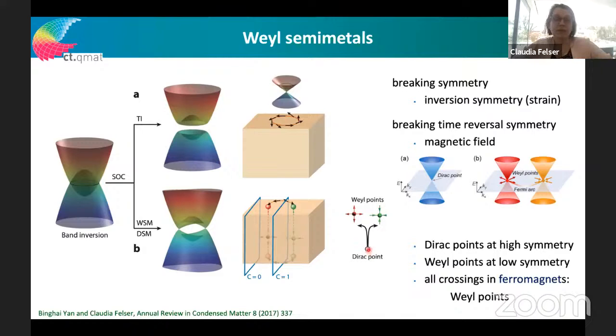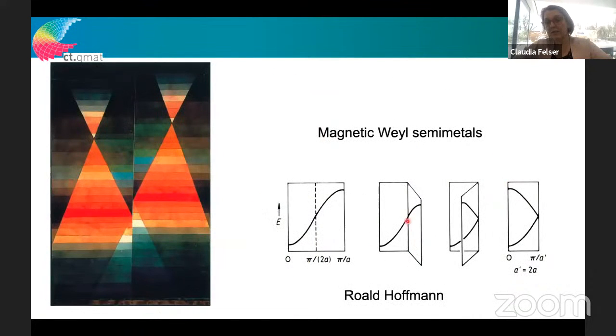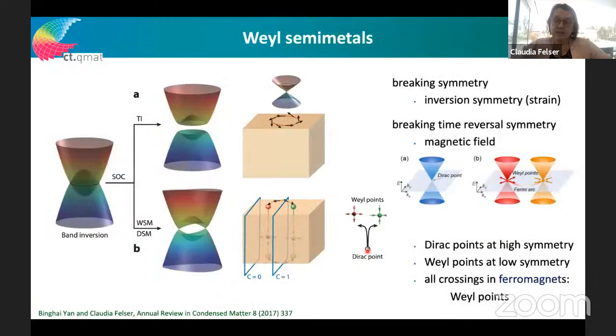Dirac points are 4 times degenerate, and they are at high symmetry points. We know this from graphene or from my nice simple picture here. If this is at the center, at a special point in the Brillouin zone, it is easy to find. And like in graphene, we have exactly the point at the K point here. So then we have it at this high symmetry point, it's 4 times degenerate. If we would now strain our graphene, we would lift this degeneracy and would end up with two 2 times degenerate points, and they are Weyl points.